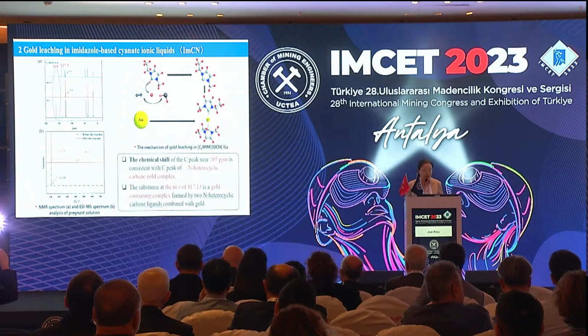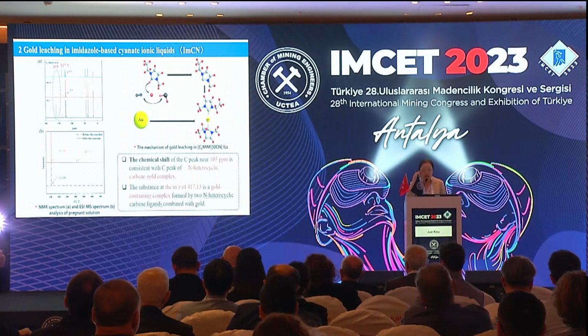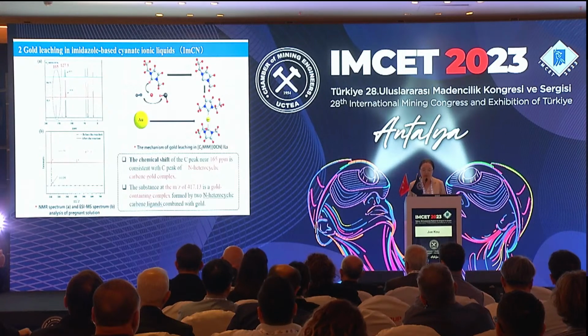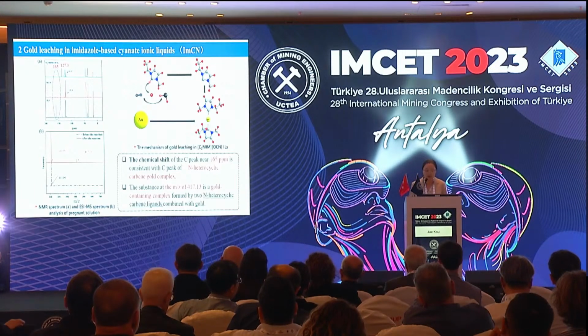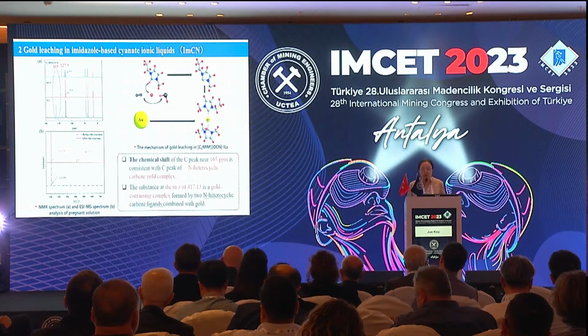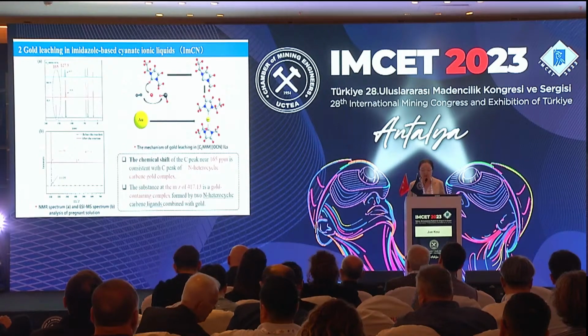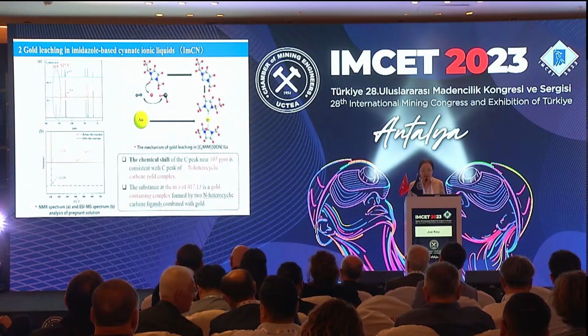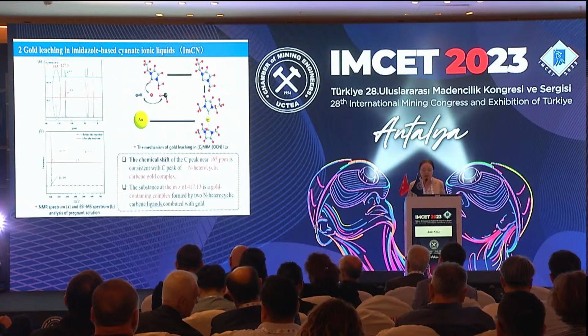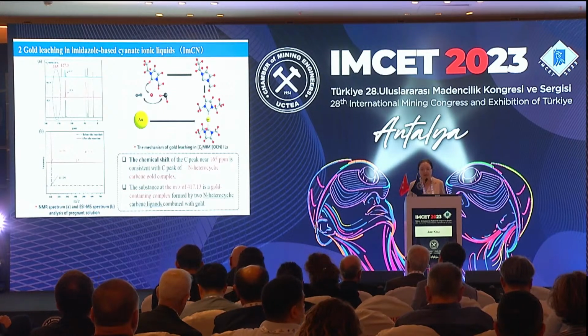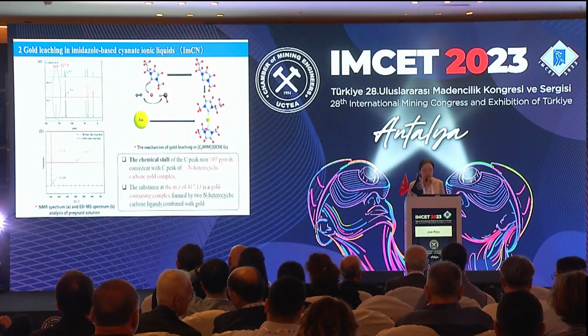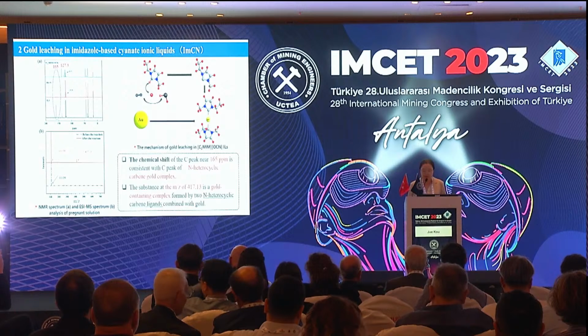And this is the NMR spectrum and ESI-MS spectrum of the pregnant solution. And here we can see that the chemical shift of the carbon peak near 165 ppm is consistent with a certain structure. This structure is called a nitrogen heterocyclic carbene gold complex, which is mostly like that, with the gold in the middle, and it is connected to the structures of the ionic liquid.